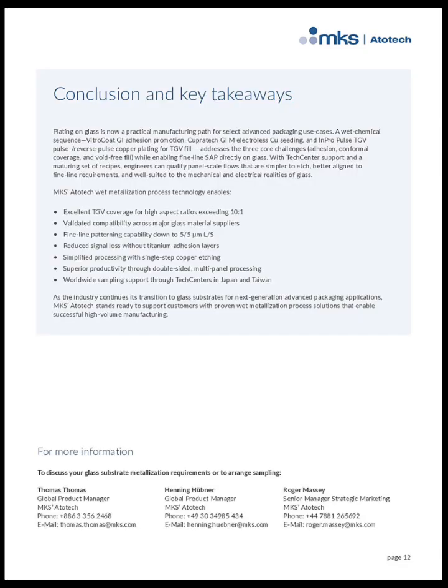In conclusion, plating on glass is now a viable manufacturing path for advanced packaging. The core challenges, adhesion, conformal coverage, and void-free filling are effectively addressed by VitroCoat GI, Atotech GIM, and InPro Pulse TGV technologies. These processes support fine-line patterning down to 2 microns, reduce signal loss by eliminating titanium layers, and simplify processing with single-step copper etching. Combined with tech center support and proven recipes, MKS Atotech is ready to help customers achieve high-volume manufacturing success with glass substrates. The references listed here provide the technical foundation for the processes and challenges we've discussed.